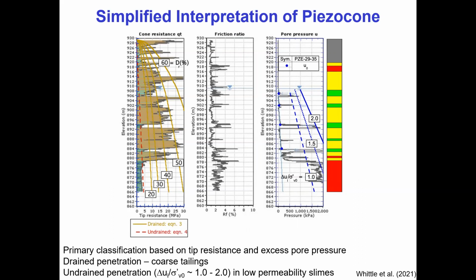In the draining areas, you can see the overlay, the relative density correlations. And you can now appreciate that versus depth, there's a huge scatter in relative density. There are many places where the relative density is less than 30%, but interpreting relative density better than plus or minus 10% is difficult. Getting the state parameter is even harder. So we decided not to trouble ourselves too much with that level of detail.